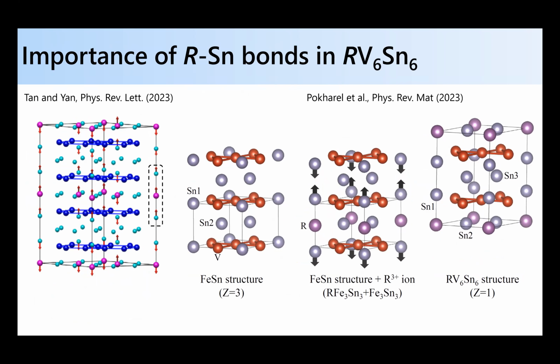Okay, so the first is to think about the structure. The 166 structure you can imagine as a variant of this 1-1 structure. Joe talked about this iron tin structure, which is a binary, and he mentioned that to stabilize the kagome net, you need to put an atom in the center of the void in these binary compounds. So then you have these tin atoms sitting there; if there was a vanadium tin compound, they would be sitting there. But then what you can imagine is, I'm going to take this iron tin structure and add a rare earth ion, and where is it going to go? In this tin 2 layer, that's a honeycomb lattice, it's going to try and sit in the center of the honeycombs. And when it does that, it's going to push the tin atoms above and below it away from it, just sterically. That means this distance gets compressed and this distance gets expanded. And then you can only do this every other layer, and when you do that, you get this 166 structure. You get effectively a bilayer lattice. Okay.